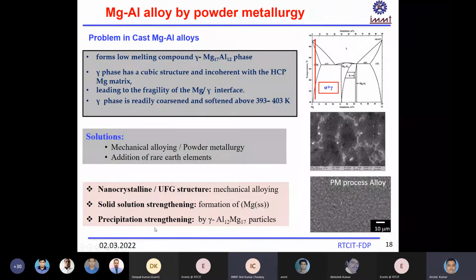And then whatever gamma phase does precipitate will not be along the grain boundary. You can see the microstructure here. You are not seeing the gamma phase form along the grain boundary. It forms uniformly. Whatever gamma phase there is will be very fine in the nanocrystalline or ultrafine grains, and distributed throughout the matrix. So that's why you can minimize the effect of the gamma phase.